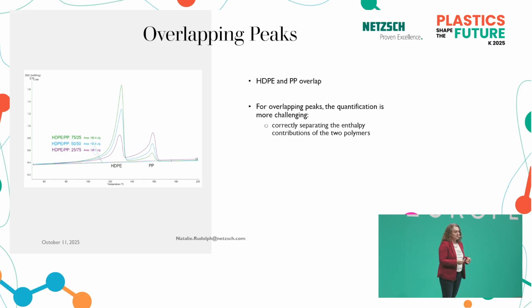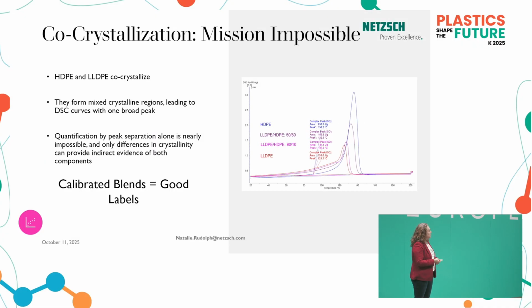Overlapping peaks, I already mentioned that once. That's where the problem starts. This, again, is still an easy case of overlapping peaks. You see that here. Overlapping means, in the case of the purplish curve, we're not getting back to the baseline. So we have to know where we actually say this first material ends and the second begins. That's where some knowledge is needed. So we need to separate that by enthalpy.